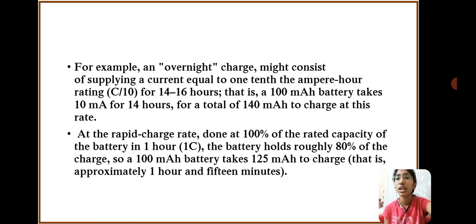At the rapid charge rate, done at 100% of the rated capacity of the battery, the battery holds roughly 80% of the charge. So a 100 milliampere hour battery takes 125 milliampere hours to charge, that is approximately 1 hour and 15 minutes.